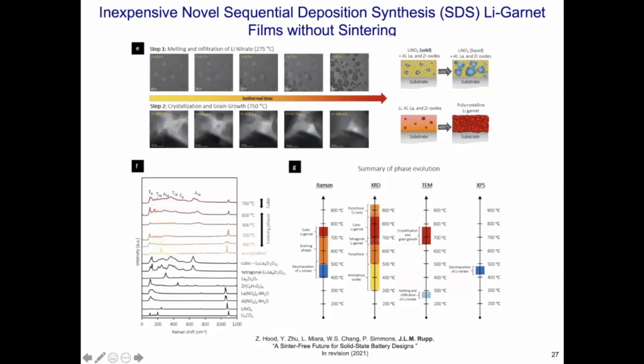And when that happens, you have coincidingly the formation of an amorphous phase first for the other cations, then a pyrochlore phase. And then once the lithium starts to diffuse, and with those various techniques which we reprobed that, we can actually see that the lithium goes into the structure and then forms from this amorphous slash pyrochlore phase later over into the cubic lithium garnet phase. But the cool thing is that it's now not made with any expensive vacuum method. So it's a really low tech, cheap way to process that.